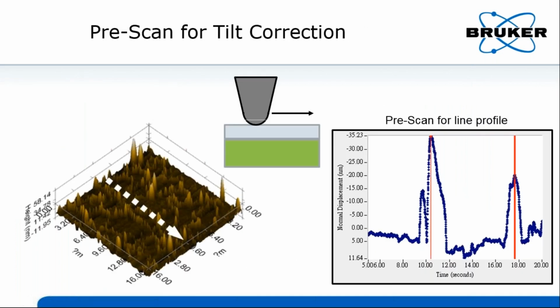Let's go back to the thin nitride film on copper case. We have to deal with the grain boundary problem for the scratch test also. One helpful thing that we can do is set a pre-scan segment for the nanoscratch test. Before the scratch, the probe is moved along the path with a small contact force of around 1 or 2 micronewton. The normal displacement data for the pre-scan segment are useful for both tilt correction and line scan profile measurement. Since the measurement path is exactly the same as the scratch path, it is useful for observation of the surface texture and roughness effects.